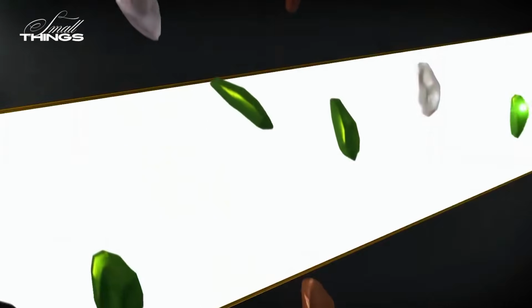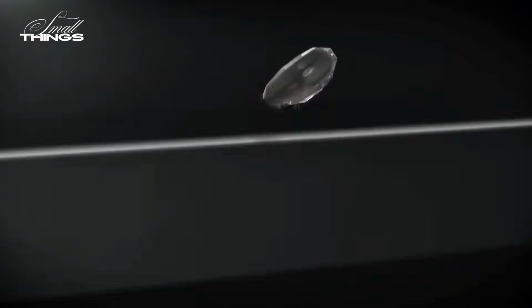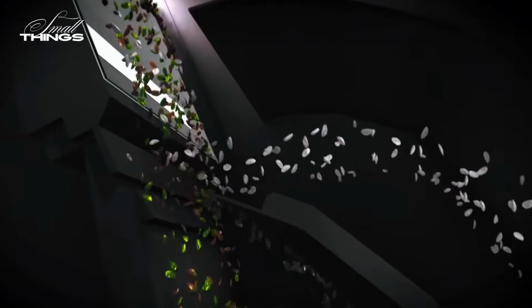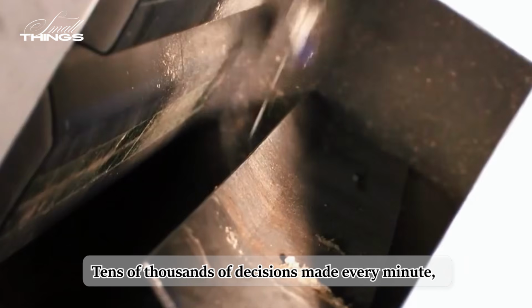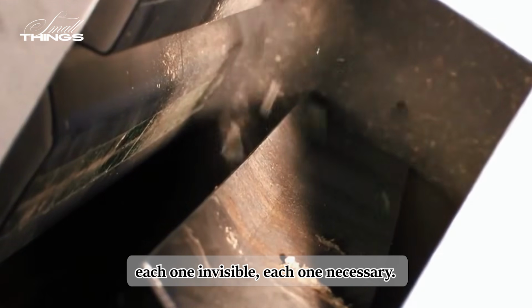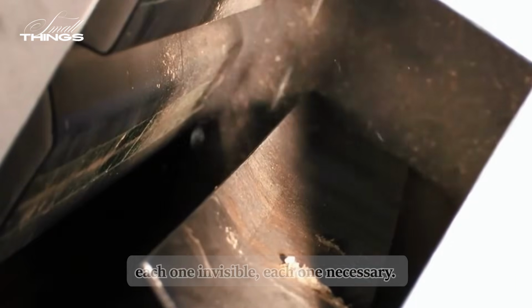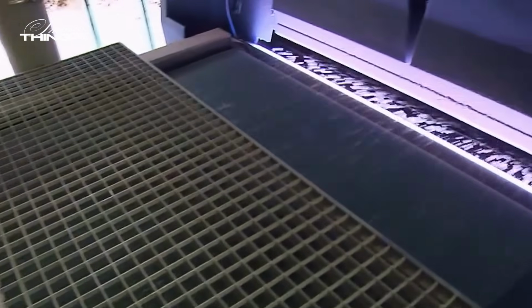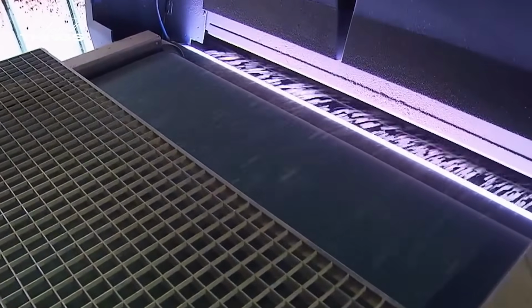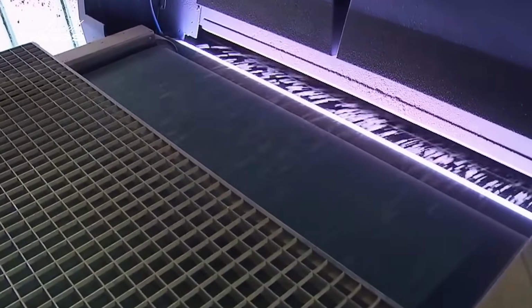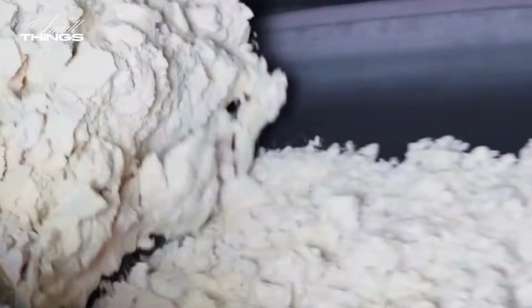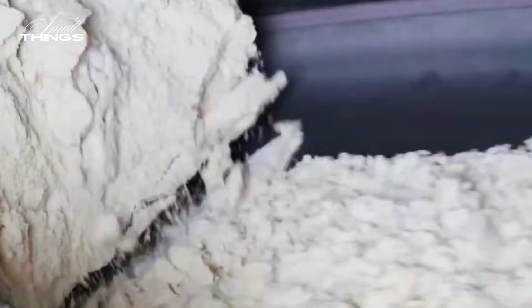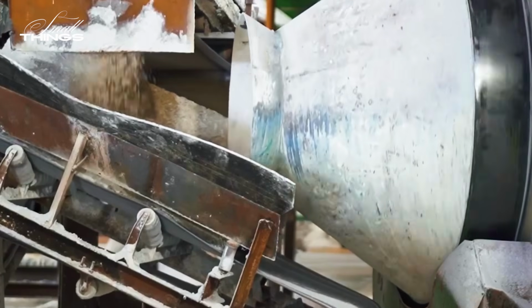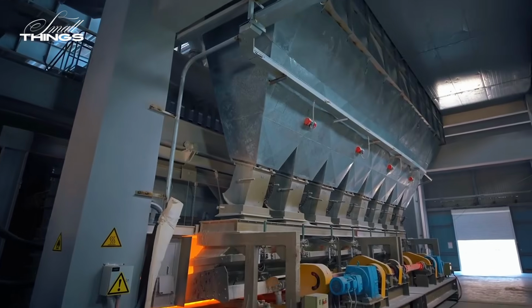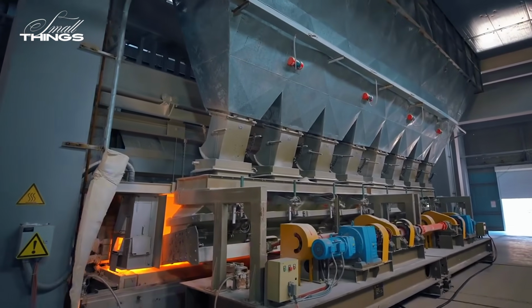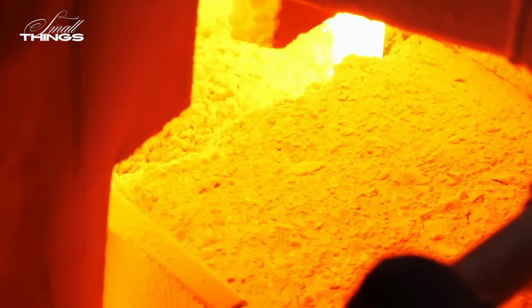The moment a brown piece appears in the clear stream, a targeted puff of air shoots it into a separate channel. Tens of thousands of decisions made every minute, each one invisible, each one necessary. Color separation matters because even a small amount of the wrong glass in a furnace batch can ruin the entire melt. The sorted cullet is blended with fresh silica sand, soda ash, and limestone, then fed into a furnace at around 1250 degrees Celsius, hotter than volcanic lava.